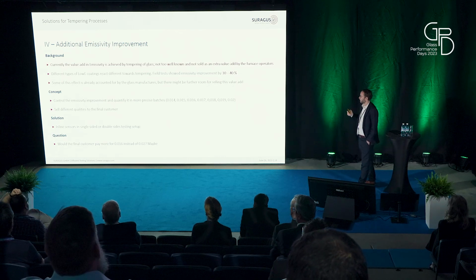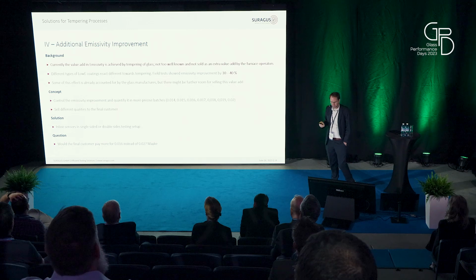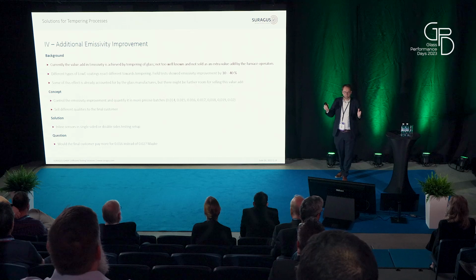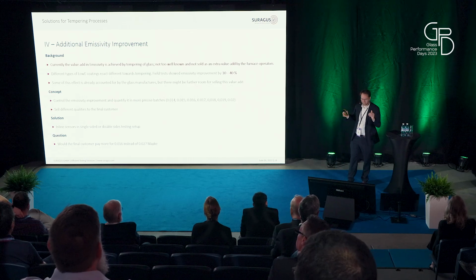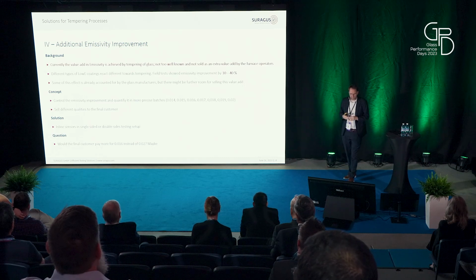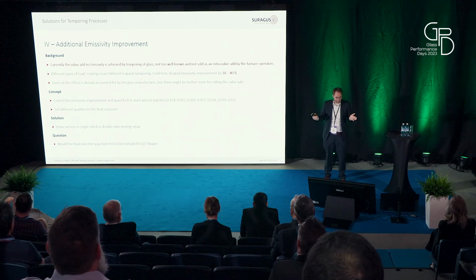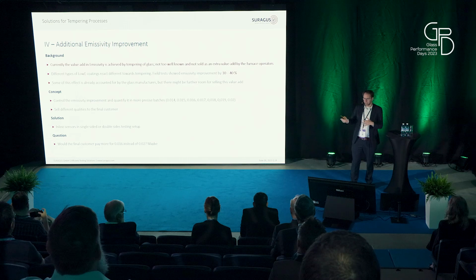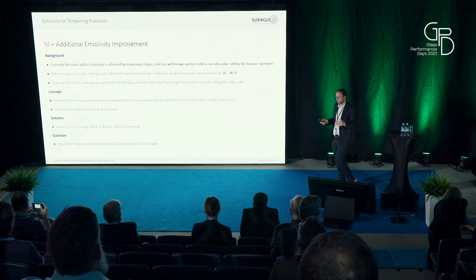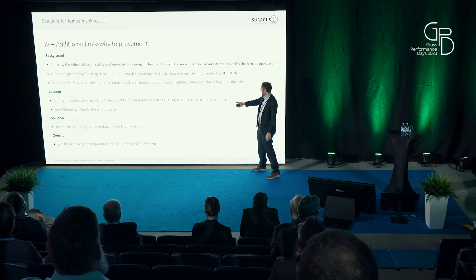The fourth idea is to use the emissivity improvement. At the moment, not many people know what the emissivity of their glass is before the tempering and what it is after the tempering. Sometimes the emissivity becomes much better than stated in the data sheet. The question is, who can use this benefit? Who can maybe also sell this benefit? If a furnace maker is able to get the emissivity not only down to this value, but maybe to this or that, then this is a clear improvement.